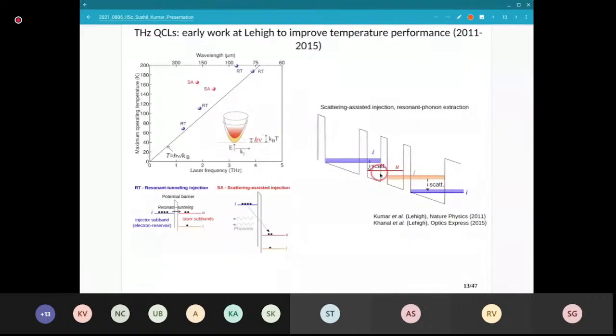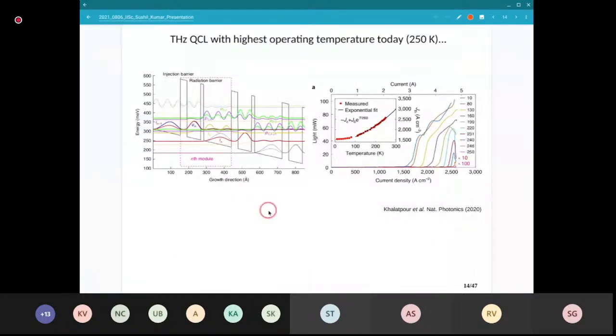Some of the work we do is trying to improve their temperature performance. This figure is for terahertz QCLs. One thing to note here: they do not work at room temperature. That's one of the challenges. As the temperature becomes hotter, it's very difficult to have this population inversion. Electrons do not stay here, they scatter and fall back into the lower level. So you have to cool them down. The best we have today is this result. They do work up to almost 250 Kelvin, which is about minus 25 degrees C or so.